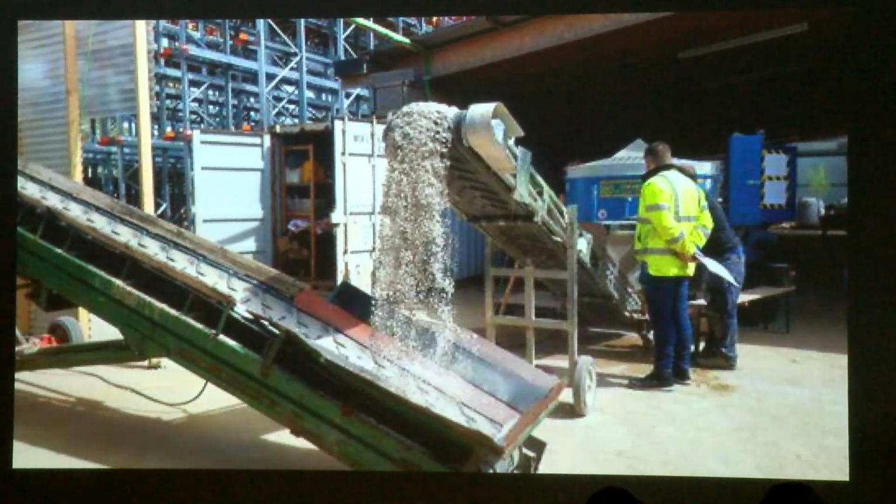That's distinct to what we're doing. It's not going through autoclaving, which is a sort of steam oven. The brick that we've developed doesn't go through anything like that. It's also made from waste materials rather than from virgin sand. And so what we are finding is that whilst it's chemically very similar to other bricks that are readily available, it doesn't actually sit within those codes, and therefore you can't make a direct application, and you can't demonstrate that it's fit for purpose against those codes.